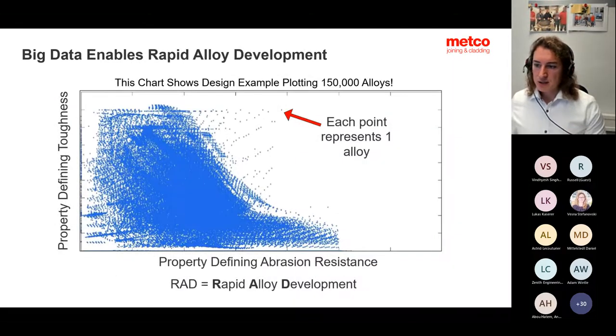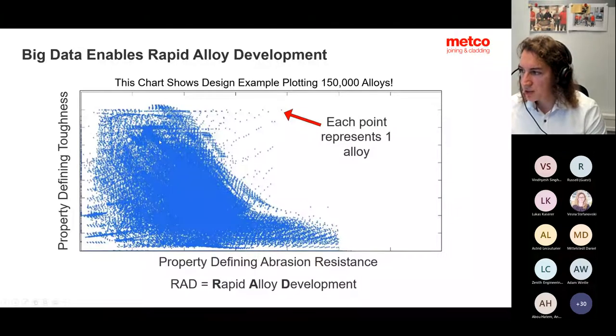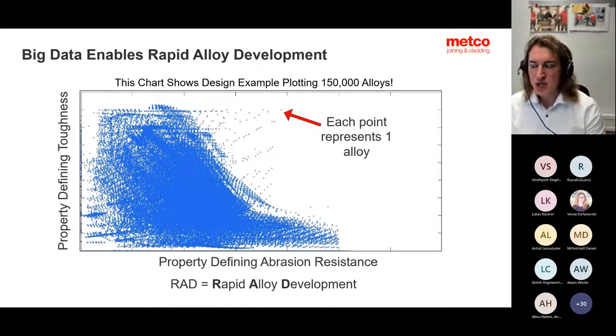So imagine this chart shows you, let's take an example, Inconel 625. Within the chemistry of Inconel 625 range or microstructure range, you can have different possibilities to impact toughness or, for example, abrasion resistant properties. And here all the blue colored spots represent each individual alloy. So on only this chart, you have 150,000 spots, which all might be an Inconel 625 microstructure, but with different toughness and, let's say, wear resistant values. So imagine testing 150,000 different combinations, which is almost impossible.